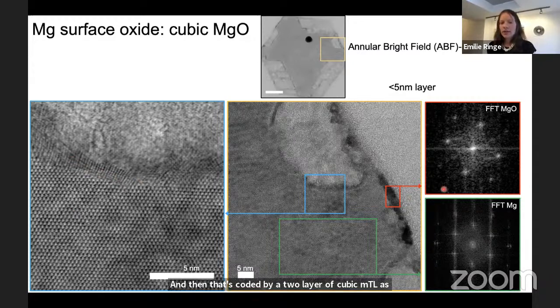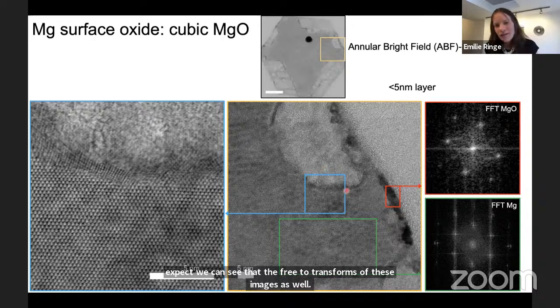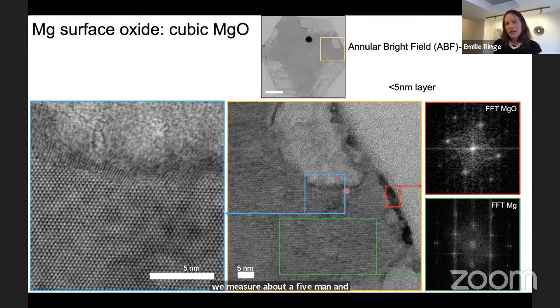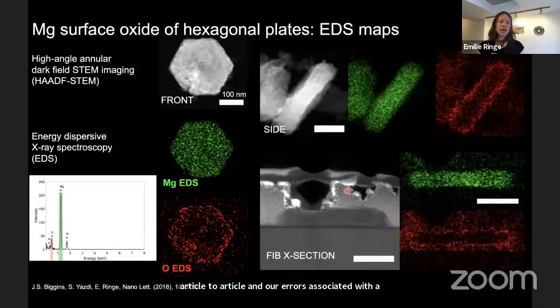As we expect, we can see that in the Fourier transforms of these images as well. Here we measure about a 5 nanometer layer. As you'll see in the next couple of slides, this thickness varies from particle to particle, and there are errors associated with the variety of ways we measure this.